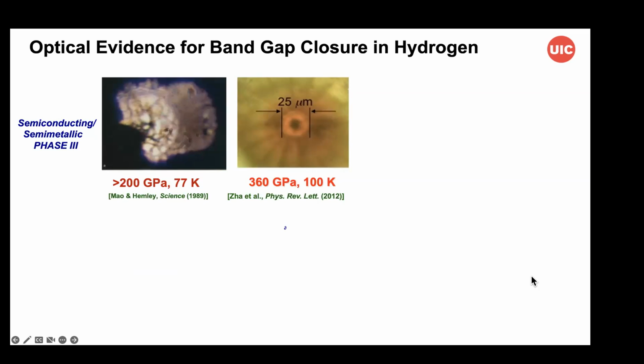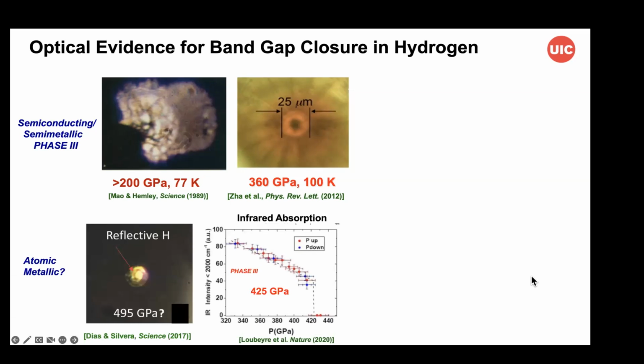We extended this with direct optical observations as well as infrared measurements to 360 GPa. In fact, this is phase 3, showing the very wide stability of this phase, a C2/c structure that had been predicted and is consistent with theoretical work and more recent work. Subsequent to this, in recent years, my colleagues have gone to higher pressure and with optical measurements found evidence for reflecting hydrogen, this possible atomic metallic form at something like 500 GPa, and then extending the synchrotron infrared measurements that we conducted earlier to higher pressure.